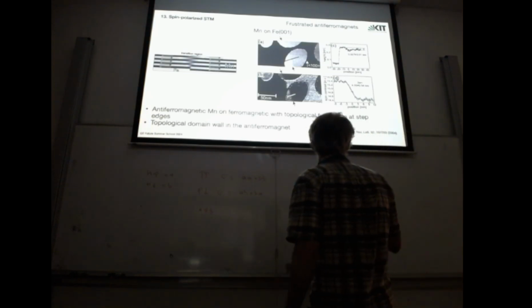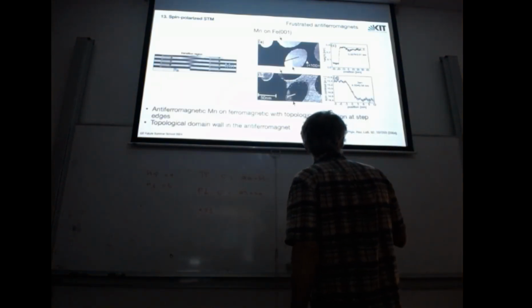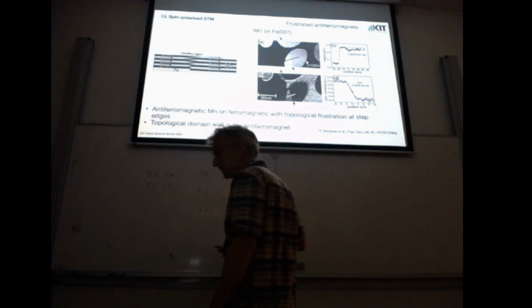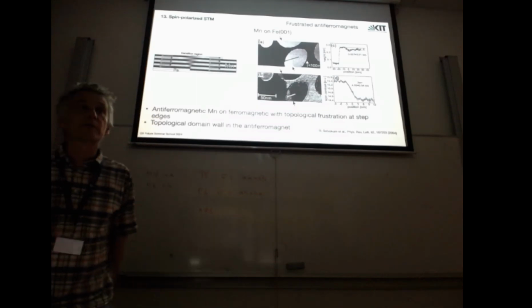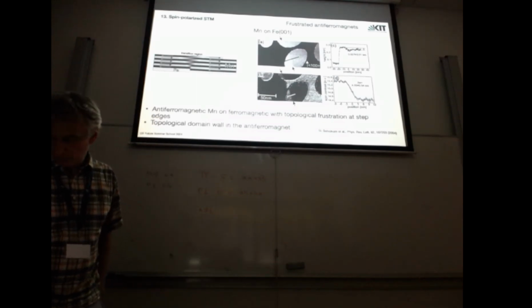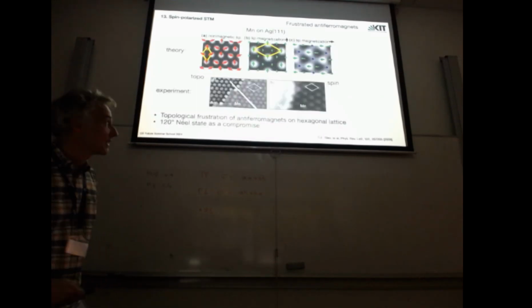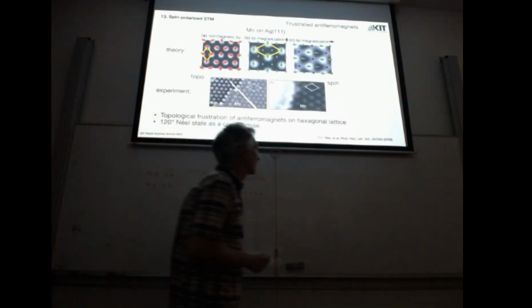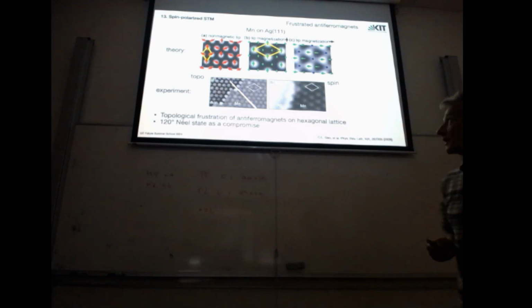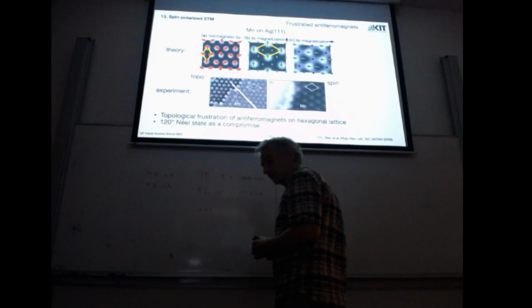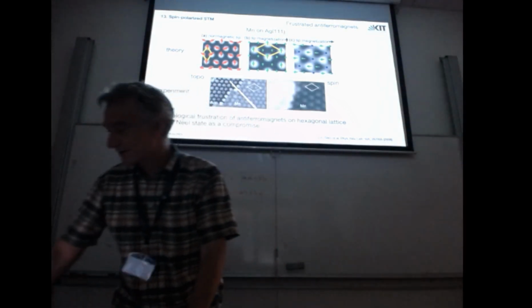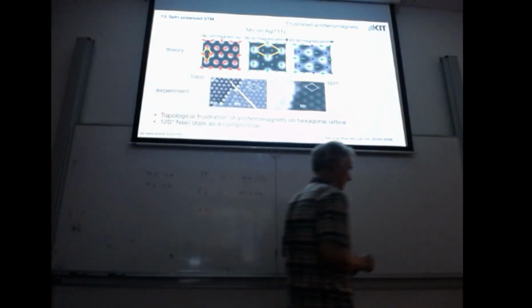And the resolution now is even better, so this is pretty sharp. How far does this go? And I give you again an example from our group. There are other groups that have done this also. Again, with a frustrated system, again manganese, this time on silver, but it's a hexagonal lattice. We take silver 1, 1, 1.